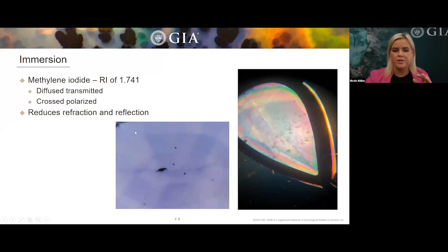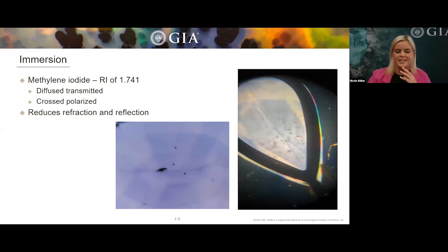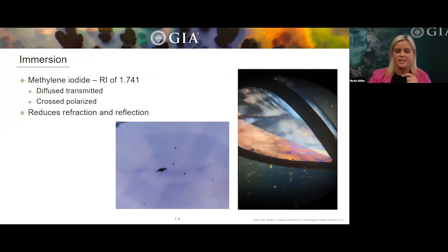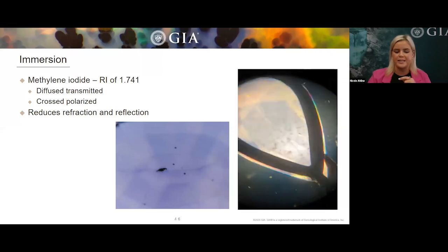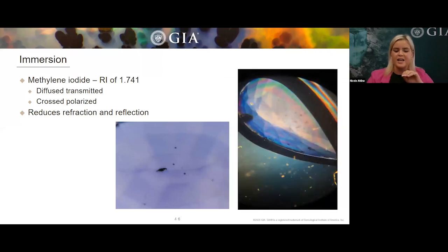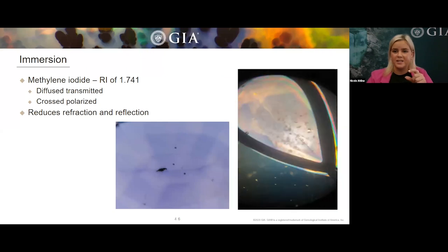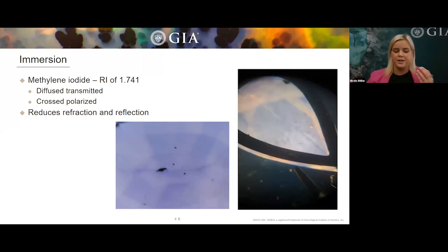So this video, I'm going to see if it'll work. Oh, great. It's a little bit loud. What we're seeing here is a flame fusion laboratory grown sapphire in immersion under cross polarized light, looking down the C axis. And what you're seeing are these Plato lines, that cross feature. Plato lines are proof that this stone has a laboratory grown origin, because they are the growth structure that is the result of excessive strain on that boule.